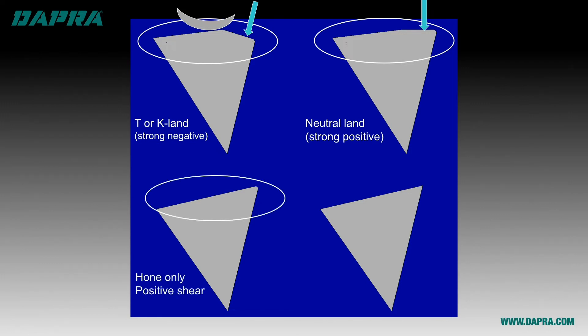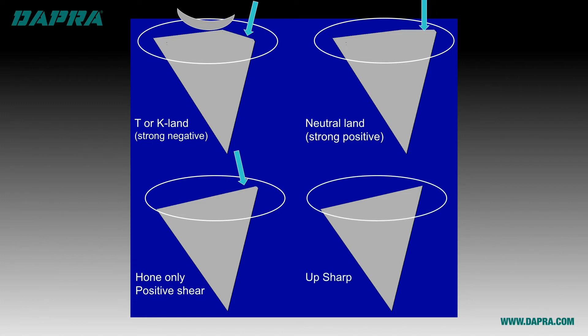The next edge shown is a honed edge and generally has little or even no land, which provides a more positive or high shear cutting action. This edge is the cleanest cutting of the three, generating the least tool pressure, temperature, and burr, but it is also the weakest in regards to shock and chipping resistance. This is generally the edge of choice for stainless steels, exotic materials, and high temperature alloys. Finally, we finish with an up-sharp cutting edge, which is suitable ideally for non-ferrous materials like plastics and aluminum, where the sharp edge is desirable and is not necessarily susceptible to chipping.